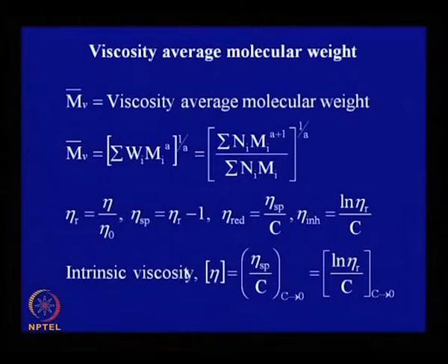So, here it is shown intrinsic viscosity. Either you can go through specific viscosity at C tends to 0, meaning infinite dilution, or ln eta relative by C up to infinite dilution.